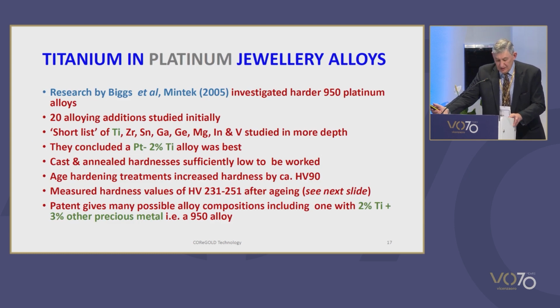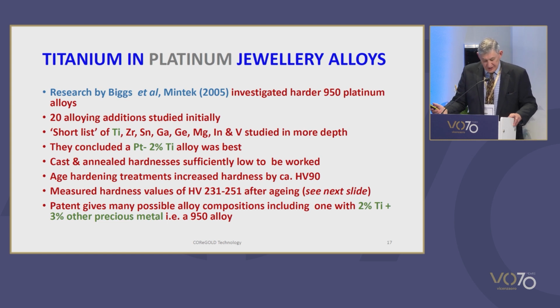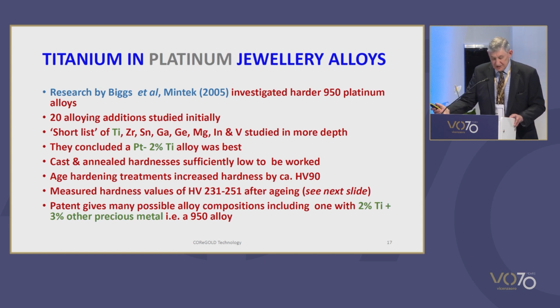Research by Biggs and her colleagues carried out at Mintek in 2005 has examined potential alloying systems for harder alloys aimed at 950 fineness platinum for jewellery application. Over 20 alloying metals were studied in preliminary trials at levels of 2% and 4% addition, and those showing promise were also studied at 3% addition. From this work, alloys with additions of titanium, zirconium, tin, gallium, germanium, magnesium, indium, and vanadium were studied in more